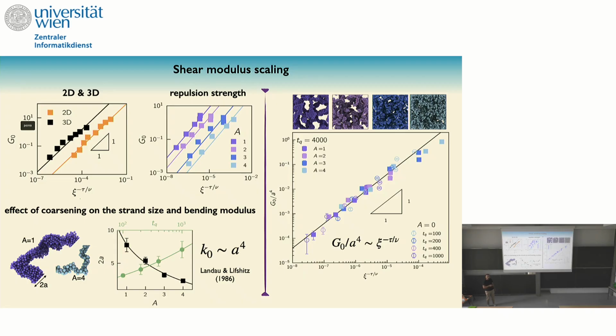If I plot all these curves, for example, as a function of the volume fraction, I would find a dependence as a power law, as I told you in the beginning, with different power laws. So I would say, no, maybe the physics is not the same. But yet, yes, it is, because there is a hidden length scale that controls the elastic property. And once you get this length scale, and once you know some properties of your rigidity percolation critical point, then everything falls onto a master curve, no matter what you do to your system.